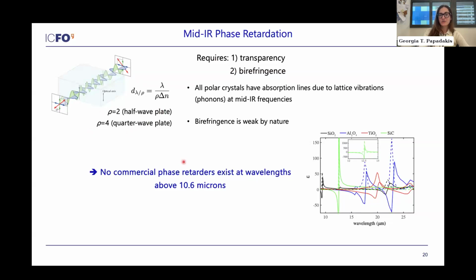So to build a phase retarder, what you need is a material that is, of course, transparent, and also anisotropic, and in particular, birefringent. So orthogonal to the plane that light propagates, you'd want it to be anisotropic. However, if you look at this plot that I showed before, all dielectric, so transparent materials in the mid-IR have these strong absorption peaks. So you can use them, but you can never use them in a broadband way because at some point they're going to absorb heavily.